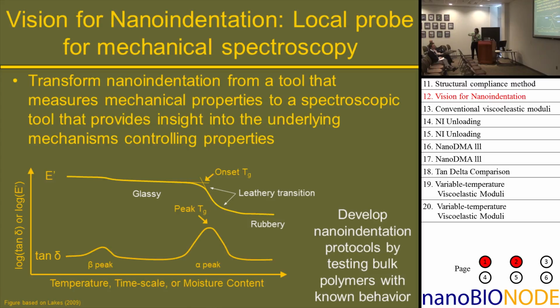So polymers have polymeric chains with side groups. You can have secondary relaxations where the side groups go through a thermal transition, and that typically shows up as a very small perturbation in the storage modulus, but you can get little peaks in the tan delta. Then, as you go to higher temperatures, the entire backbone goes through a thermal relaxation, which can cause a large decrease in the elastic modulus of the material, and also a large peak in the tan delta. And there are different ways to define a glass transition.